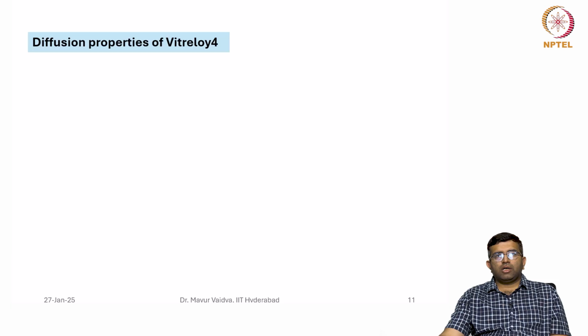Now here I just want to tell you some features of the diffusion properties of Vitreloy 4. This Vitreloy 4 is an important glass forming composition, which is zirconium, titanium, copper, nickel and beryllium. Zirconium and beryllium are the major elements, zirconium being 46.7, beryllium 27, and the rest three are present in smaller amounts.